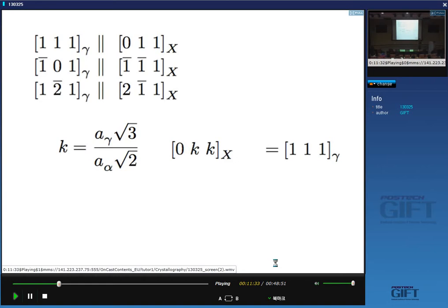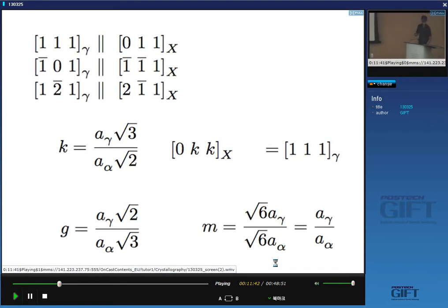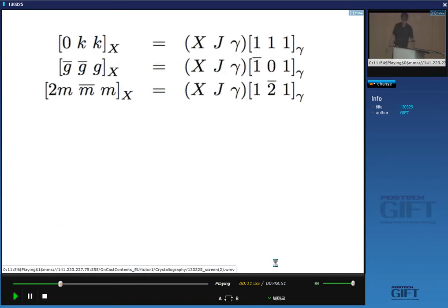Yep. So this will become A gamma into root 2, and this will become A alpha into root 3. So here we are, A gamma into root 2, A alpha into root 3, and similarly for this one, we have root 6 A gamma over root 6 A alpha, which is just the ratio of the two lattice parameters. And therefore, I have three equations here, 0 kk,